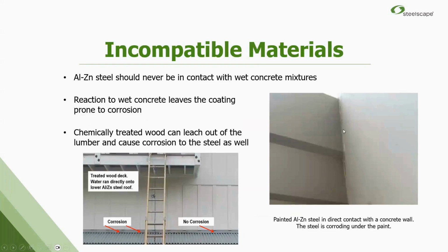Same house, by the way. Here on the right is the one prior. They poured concrete right up to the metal panels without a water barrier between them. So the moisture from the concrete is leaching into the metal panel and causing corrosion and failure of the paint system. On the bottom here is treated wood. A lot of wood is treated with copper. Copper and painted Galvalume, painted galvanized product don't get along very well. So the water was leaching out of this deck up above, running down onto the panels below and causing corrosion. As soon as you got away from that deck, the panels were performing as expected.